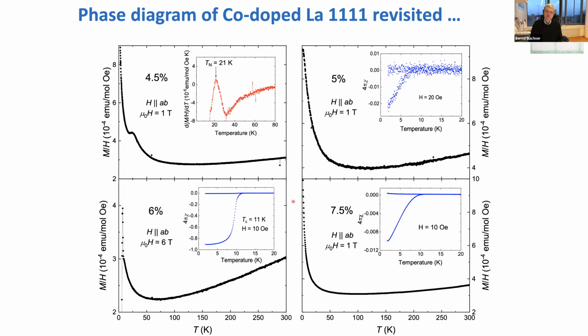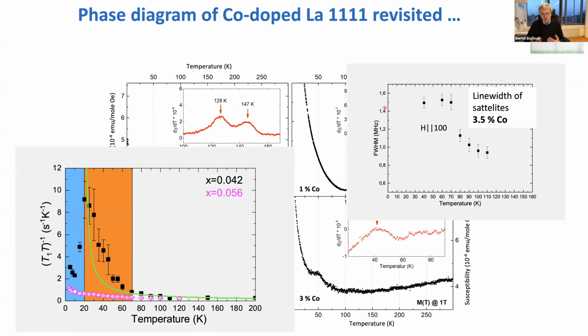If you go to higher doping, systems become reasonably good superconductors. Optimally doping, TC is small, but this is known because cobalt impurities reduce TC. But it's also clear that you see magnetism disappears at about 4.5%. Superconductivity is very strong with 6%, and in between we have, let's say, very weak superconductivity and no magnetic order. So we used also NMR to study the properties, and that confirms the things which you get from the macroscopic properties. So you see this very strong change of 1 over T1 when the magnetic order is still present, and then it disappears and we lose the long range order. We can also, looking at the satellites, determine there the structure phase.